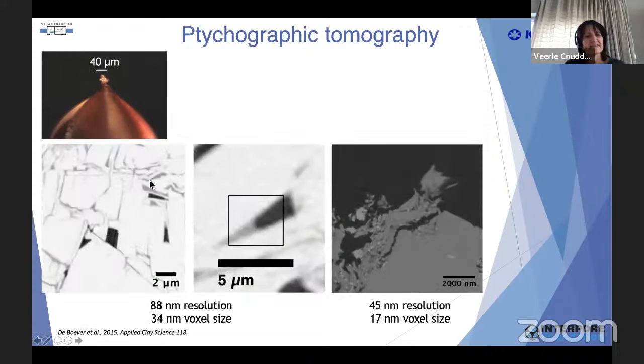So when we scanned this, we were able to look at our case, and these were the results. This experiment was done, I think, in 2014. The voxel sizes we could reach were in the order of 34 nanometers and 17 nanometers, and we had the internal structure in 3D.